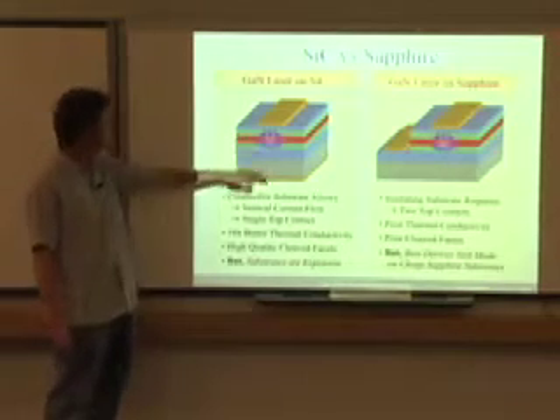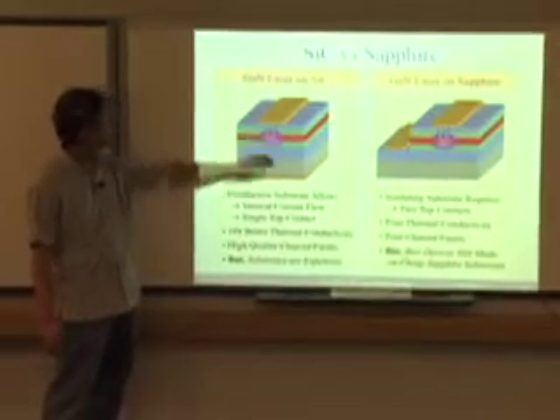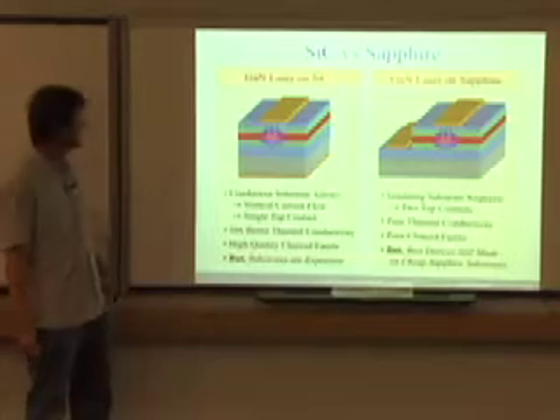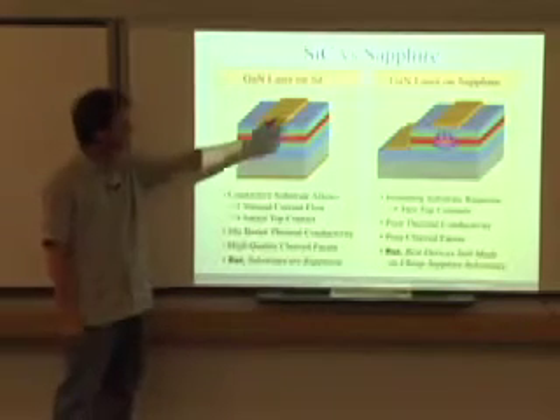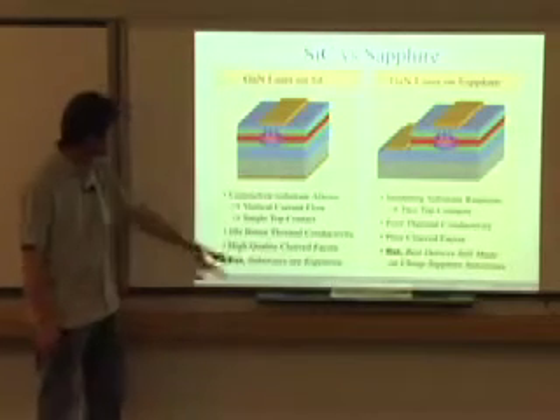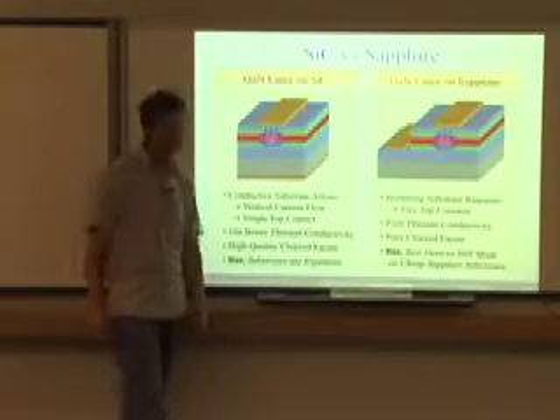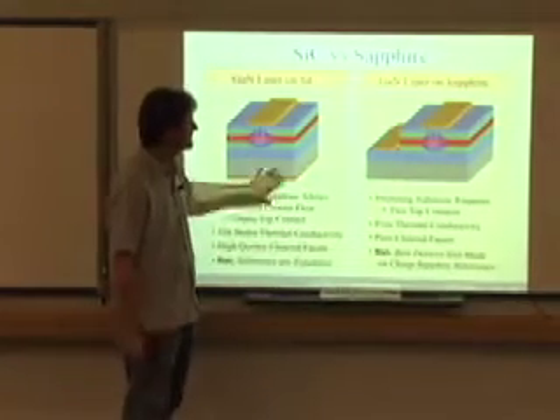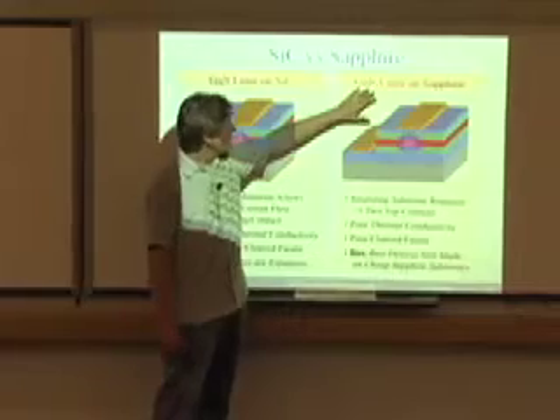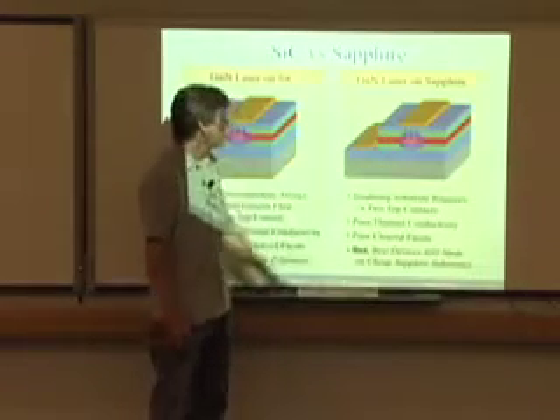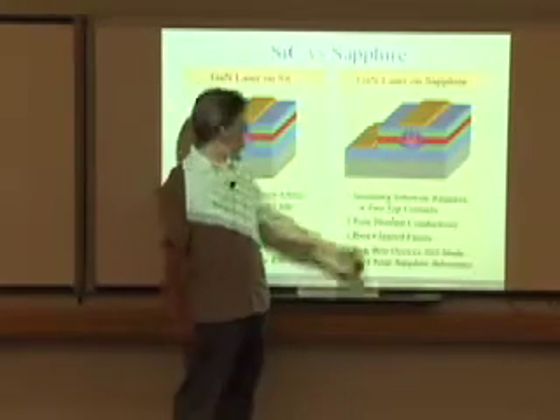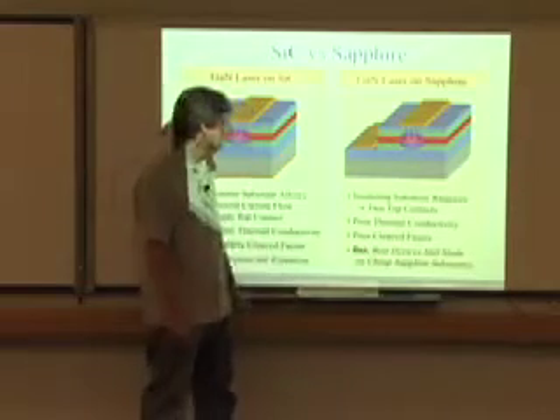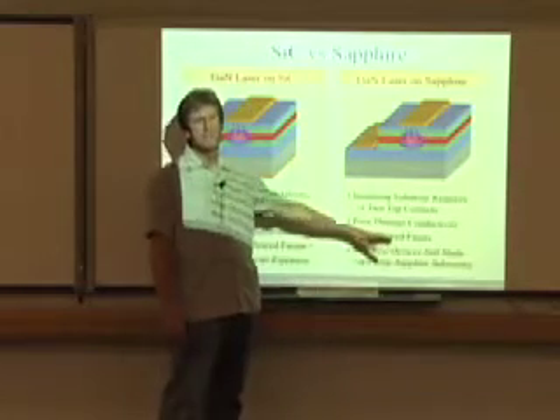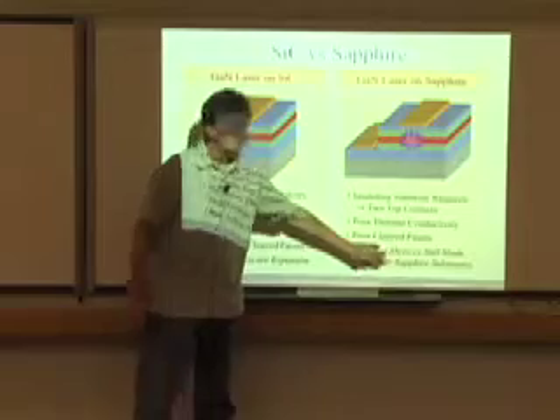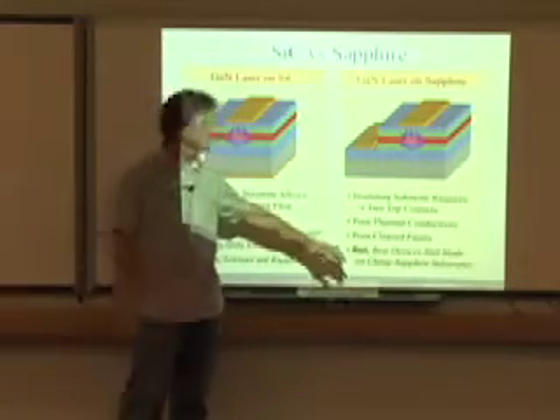Then comparing silicon carbide to sapphire, there's some advantages with silicon carbide. It has a conductive substrate, so it allows for vertical current flow. You have a single top contact, better thermal conductivity than with sapphire. However, the substrate's very expensive, and so that's kind of a limiting factor for using silicon carbide. Gallium nitride layer on sapphire, it's an insulating substrate, so it requires 2 top contacts, there's poor thermal conductivity, poor cleave facets, as I'll show you in a minute. But the best devices are still made, well, at the time, were still made on cheap sapphire substrates.